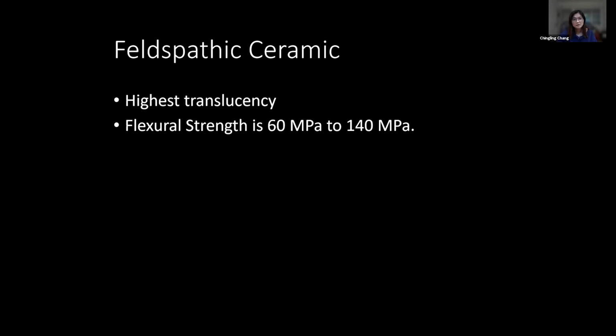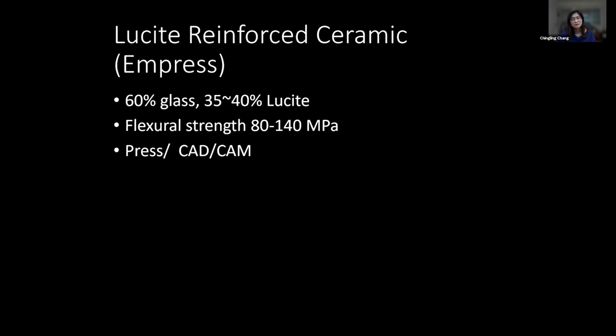The feldspathic ceramic actually has the highest translucency, so it has a very good aesthetic result. But it does not have very good flexural strength. It's only from 60 megapascal up to 140. Then the Ivoclar company came out with a leucite reinforced ceramic, composed of 60% glass with leucite to increase the strength. So the flexural strength can go up to 80 to 140 megapascal. It's higher, but still not very good for posterior teeth. And to fabricate that, you can use press ceramic or use the CAD/CAM technique.